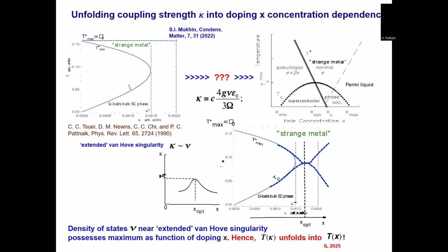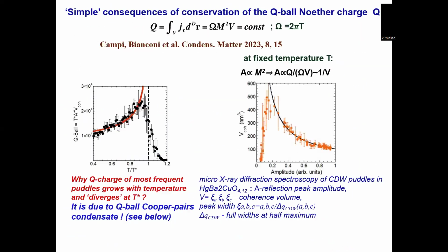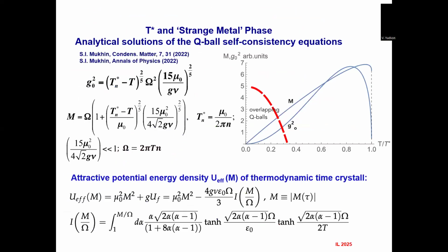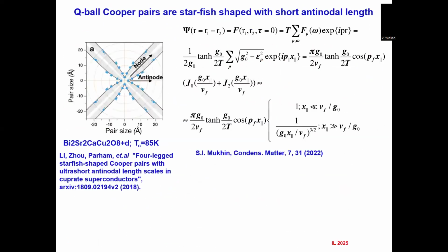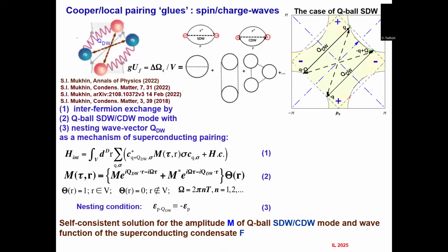But the QDW vector, what direction is it? Let me find in this strange PowerPoint file. There should be a plot. Yes, here is the plot. This is what people see, because here would be hole pockets in lightly doped material, and they see this kind of Fermi surface in 2D in the AB plane. Then these are so-called anti-nodal points, which we consider as nested, but in this strange way nested with a Q-ball field.